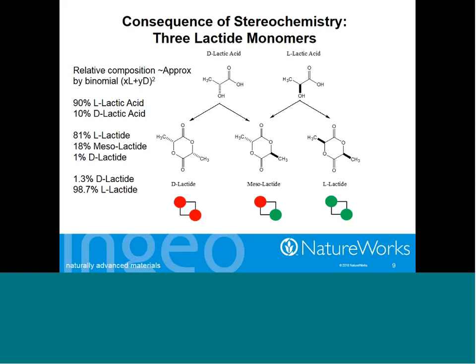As I mentioned, the oligomerization process has some thermal history to the lactic acid, and that allows us the opportunity to interconvert some of the L-lactic acid to D-lactic acid, and that allows us then the opportunity to make mesolactide and some D-lactide. Now, the composition of that lactide stream can be approximated by the binomial that I've shown here, the mole percent of L-lactic acid and the mole percent of D-lactic acid squared gives you nearly the relative ratios of lactides that we're going to make.